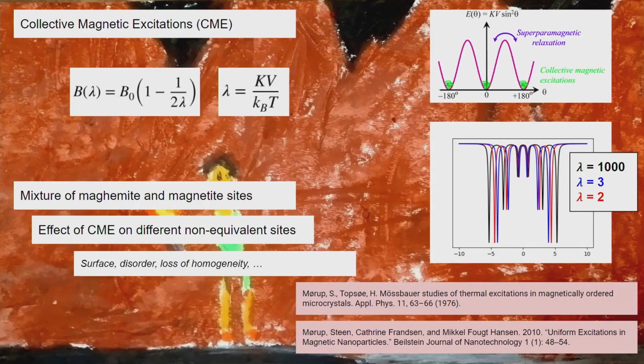The first thing that we know was happening is collective magnetic excitations. That is something introduced by Mørup and Topsøe in 1976. I was 1 year old at this time. It has to do with a monodomain particle: if it has a very fast relaxation time, it will behave like a paramagnet, because it is half and half on both sides. It has a null hyperfine field, but if the time is shorter, it will be only in one of the two wells.